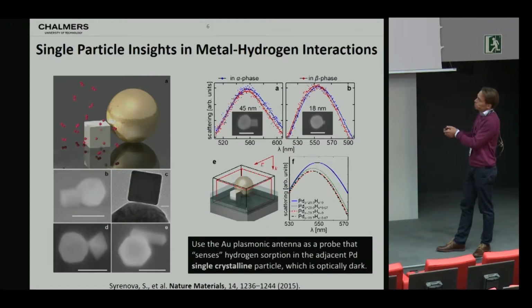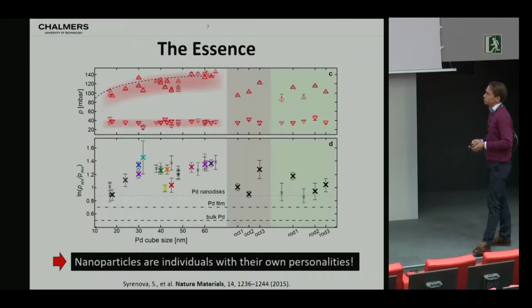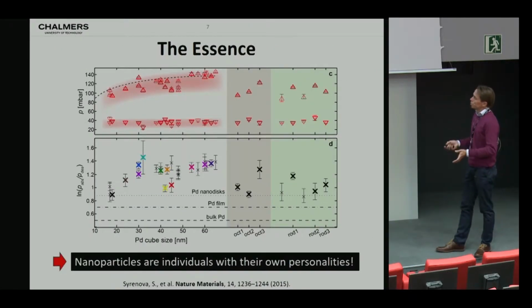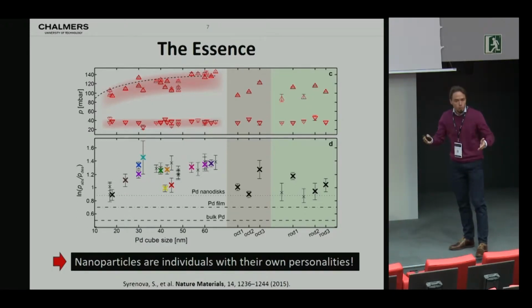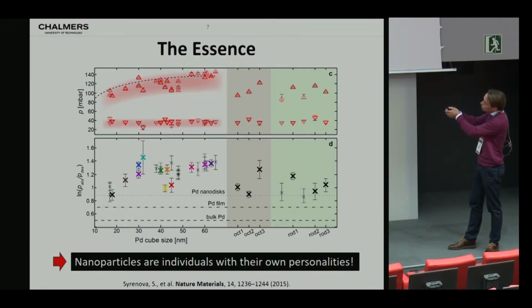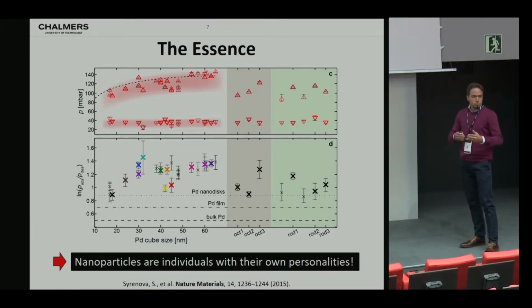So the idea is that palladium nanocrystals absorb hydrogen. At a certain hydrogen pressure, they form a hydride phase. This induces a shift of the scattering spectrum, which we can detect, and if we can make such dimers, we can look at how size and shape of these nanocrystals affect this process. And in essence, what we find in this quite busy graph, if you plot as a function of the side length of the single crystalline nanocube the pressure at which they absorb a lot of hydrogen, is that even for nanoparticles which essentially have exactly the same size, that pressure can be up to 40 millibars different.